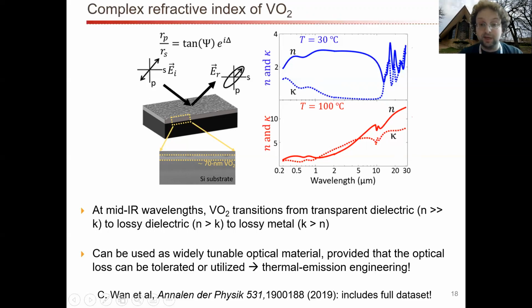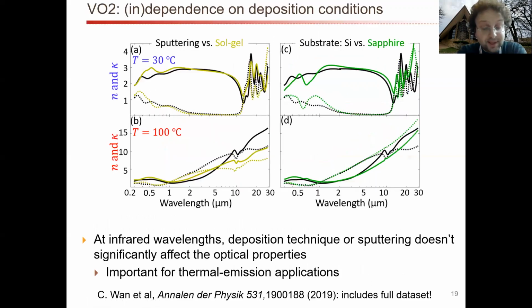And so if you take a look at this paper and you look at the supplementary, we included the full data set. You can copy and paste it in your simulations, and you can do VO2 simulations at pretty much any optical frequency that you want. Another thing that we found digging into the literature is that every time you see a VO2 data set somewhere out in the literature, it's different. If you pull up one paper, you get one data set. If you pull out another paper, you get another data set, and they don't agree at all. And so we wanted to really figure that out.